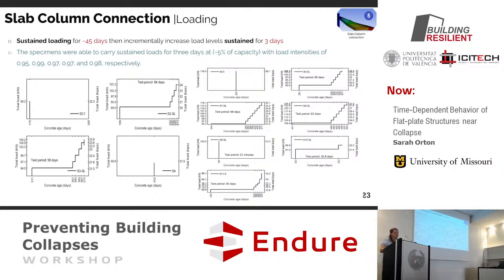These tests, again, we're putting under sustained load. Most of the tests did not fail under the first sustained loading period. So we'll load it up. This one was to 89 kilonewtons and leave it under the load for almost 45 days. And then if it didn't fail, we put a little more load on and leave it under the load for 3 days. And if it didn't fail, you put a little more load on. Just incrementally approaching that to see when we could get that sustained load failure.